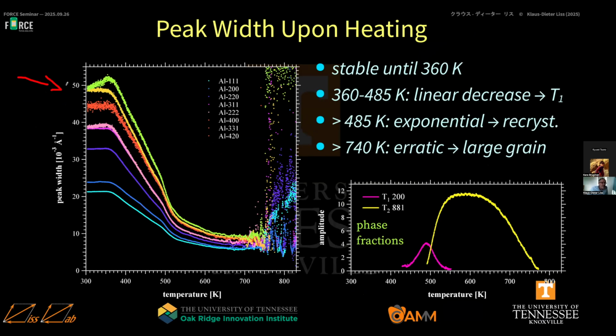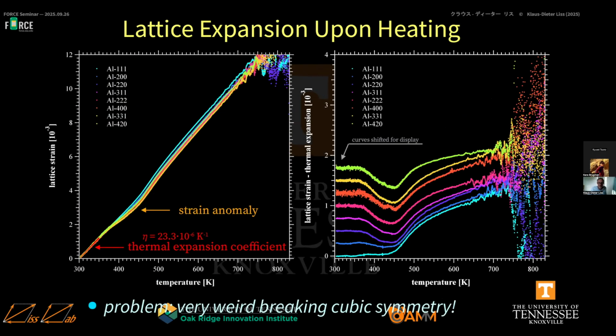We can look at the peak width, and the peak width goes down as a function of temperature. And this is the recrystallization process. So during recovery and recrystallization, when you do a Williamson-Hall plot, you measure the peak width, and the breadth of the peak is related to the grain size and also related to the intergranular strain due to intergranular gradients and stresses. We can look at thermal expansion. So this is thermal expansion, and we see there's a strain anomaly. I can subtract this straight line and get the figures to the right.